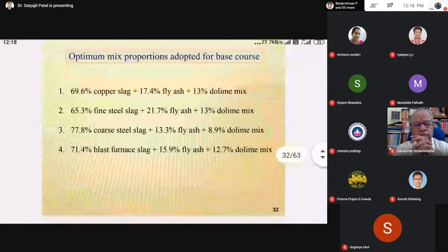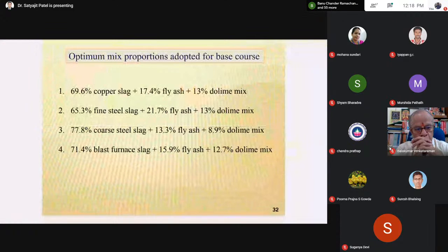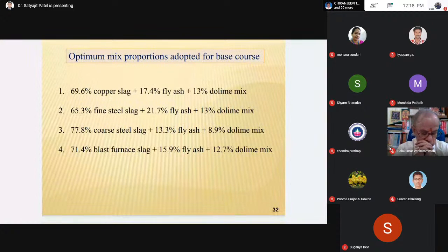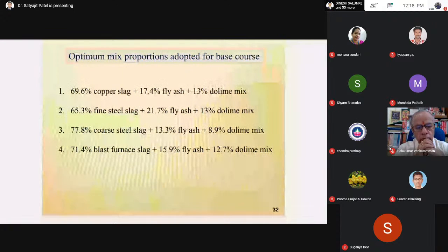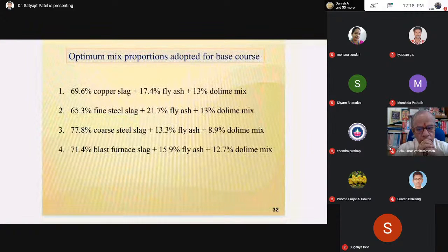The optimum mix proportions adopted for base course: similarly for all the materials, all these tests have been carried out, and based on these tests, the optimum mix adopted is 69.6% copper slag, 17.4% fly ash and 13% dolime. This gives the best result of the maximum value. Similarly, fine steel slag optimum mix, coarse steel slag and blast furnace slag optimum mixes are there. They give the maximum resilient modulus value, and also fulfill the strength requirement given by IRC 37 to be used in the base layer of flexible pavement.